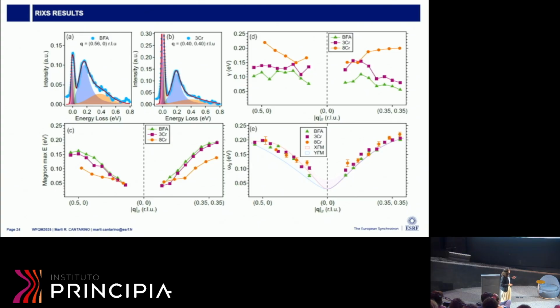When you translate this into the fitting model, so I have a bare frequency and a damping factor, I see that the damping is much bigger for the 8.5% chromium sample, but the bare frequency is very constant. Then I compare this frequency with linear spin wave fittings from inelastic neutron scattering data, and it's very similar.